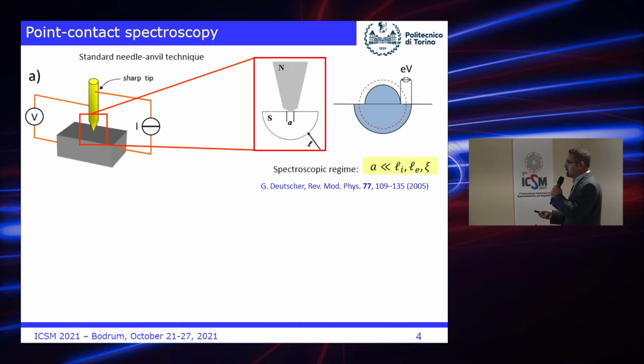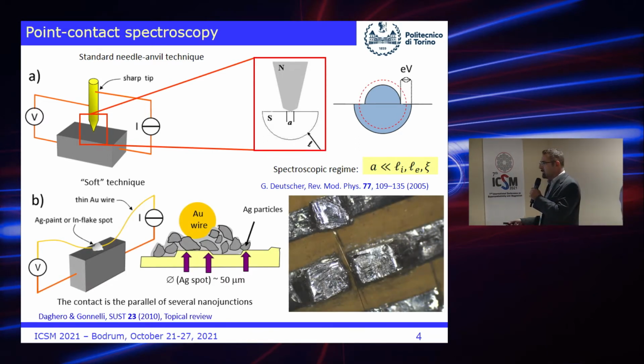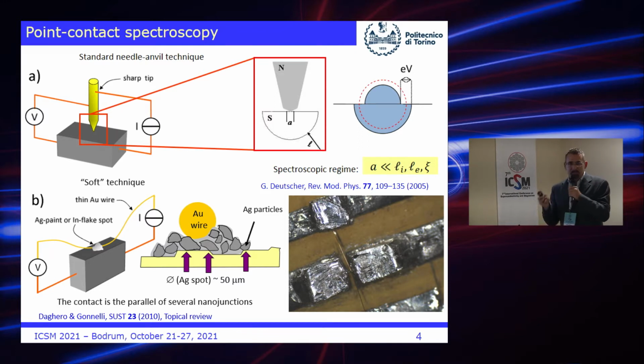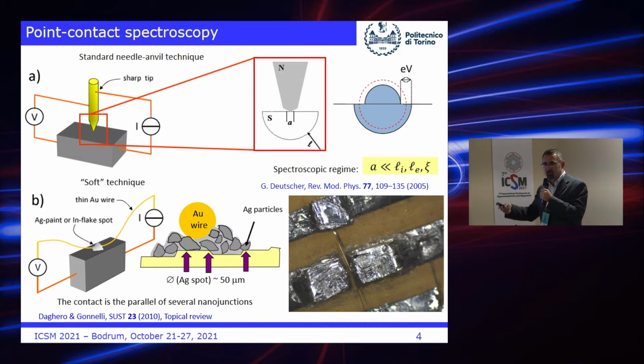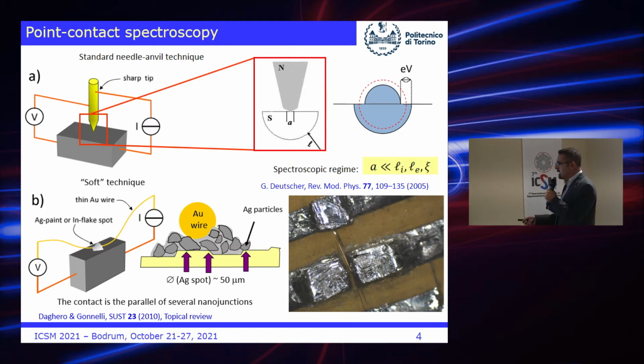This means that the size of the contact has to be smaller than the inelastic mean-free path and of the coherence length. If it is also smaller than the elastic mean-free path, much better, because there is no diffusion, no elastic scattering. Then we actually used another setup, the so-called soft technique, in which instead of the tip we used a small drop of silver paste. Clearly, small means of the order of 50 microns, so certainly this is not in these conditions, but fortunately we can anyway see spectroscopic signals, and the reason is that we have several parallel nano-junctions between individual grains in the paste and the surface of the material.